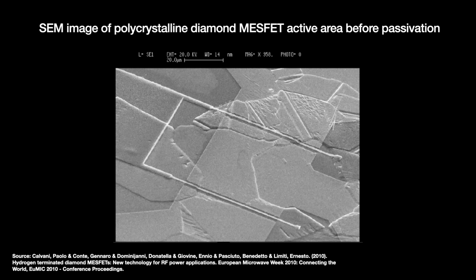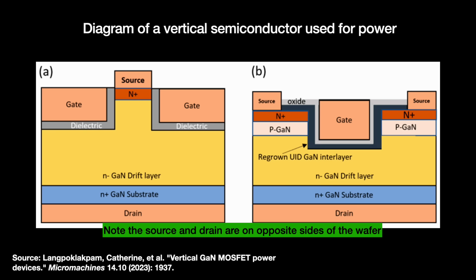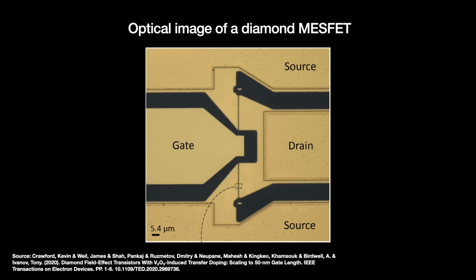But major challenges remain. For instance, the transistors in modern power electronics are vertical, with the source and drain on opposite sides of the wafer, because it lets a power current flow through the bulk of the device for heat, efficiency, and voltage reasons. In the diamond MESFET, power flows only through the thin oxygen or hydrogen terminated layer at the surface of the device. Changing this means fixing the doping problem again. So yes, we're rather far from diamond transistors that can compete with silicon carbide or GaN power electronics.